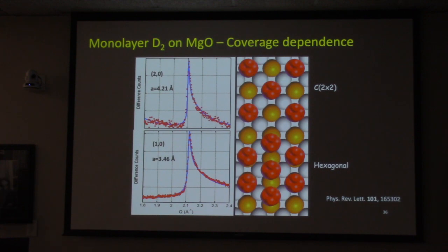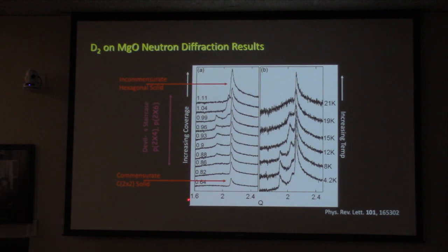And that hexagonal phase is actually more dense than any of the bulk phases, stabilized by this interaction with the surface. You can do these measurements as a function of density. Put more and more molecules in, it turns out that the structure changes. And it's really beautiful, and for experts, it turns out that it's what's called the devil's staircase.